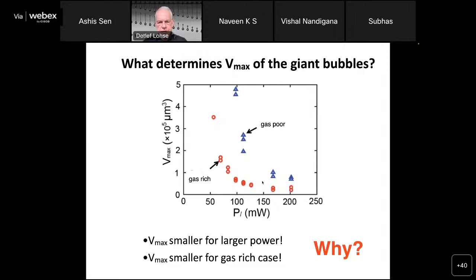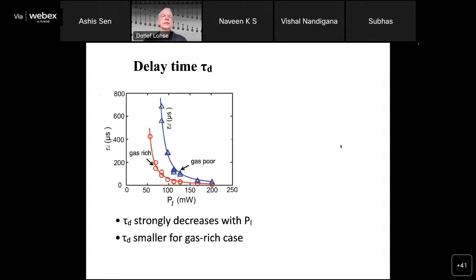What you would also expect is that when you add some gas, then you should get larger bubbles. But this is not the case either. The red curve is the gas-rich case, where you say, okay, it's more gas, there should be a larger bubble, but this is not the case. The gas-poor case creates a much larger bubble than the gas-rich case. So there are two huge surprises, and I will now explain why this is the case.